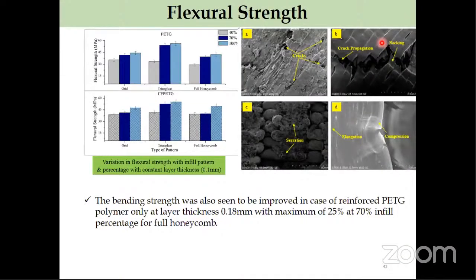In case of bending strength also, we could see that the carbon fiber addition improves the bending strength. And we could see from these images how the crack propagated and how it is following those interbonding regions. The crack is propagating through those regions. So if the bonding is good, your fracture will be delayed. That was one observation. And we could see the bending strength was improved in case of reinforced PETG only at a layer thickness of 0.1 mm, with a maximum of 25% at 70% infill percentage for full honeycomb. So that was about flexural strength, which improved.